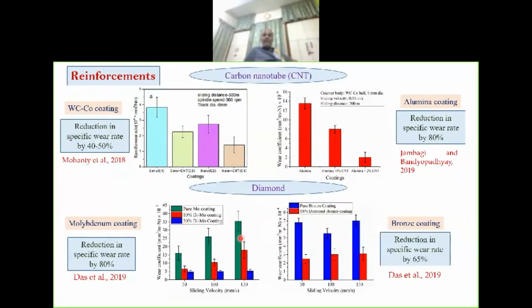Similarly, for wear purpose, we can use molybdenum coating with diamond and without diamond. With diamond, we can use bronze coating as well. This is for wear. The same improvement is also possible with lubricity. If you have a suitable additive that mixes well and is compatible with the matrix, and that gives you some good properties, it's possible. Another restriction is decomposition at high temperature. That is not permitted.